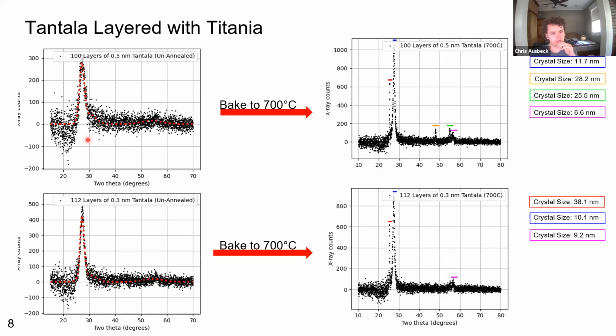If we look at these 2 crystallized samples and we bake them to a higher temperature, we see that the main peak, the blue peak here, has gotten thinner. But more importantly, we see another red peak to the left on each of these samples. And what's interesting here is that this red peak goes all the way up to around 40 nanometers large for the crystal size. And this indicates that the crystals have grown throughout many layers. So it doesn't seem that layers this thin are effective in stopping the growth of crystals.